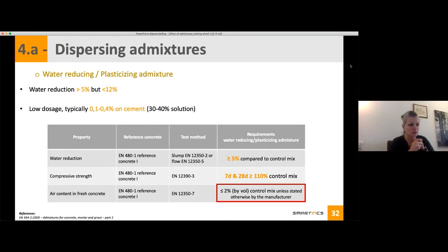It was also mentioned by Michael that the air content inside your concrete can really negatively impact it. As a rule of thumb, you can consider that for every 1% of extra air you have in your concrete mix, you have a loss in strength of 4 to 5%. So that's why you can use admixture, but you should be careful that you don't have more than 2% extra air.